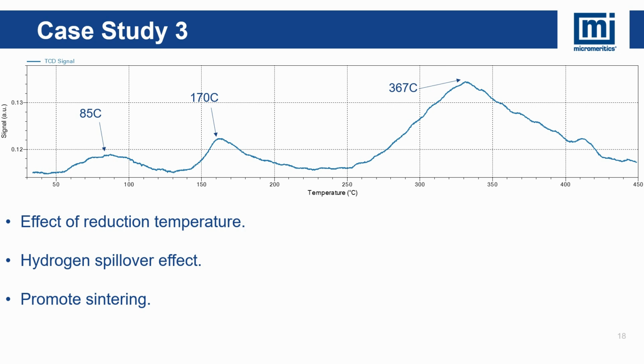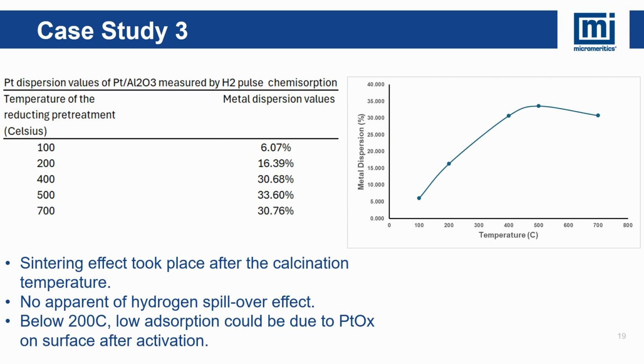Before conducting a TPR experiment, it is important to know the calcination temperature of your material. After conducting multiple post-chemisorption experiments at different reduction temperatures, the dispersion values increased as the reduction temperature rose up to 500 Celsius. Reduction temperatures of 100 and 200 Celsius showed low dispersion values, suggesting the presence of platinum oxide on the surface, which likely limited adsorption after activation. Overall, the adsorption uptake peaked at 500 Celsius.